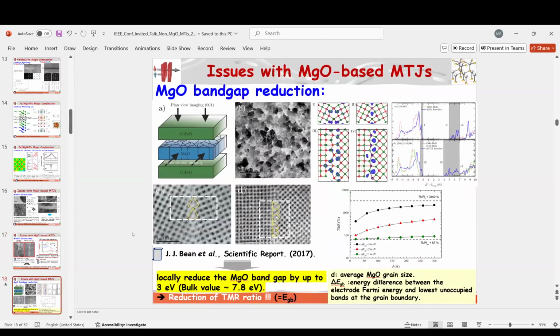I like this paper. It was published by York University and Tohoku University as a collaboration, Scientific Reports 2017. So they gathered the information from TEM, top view, cross view, they included DFT, and they tried to approach the experimental TMR ratios obtained experimentally. And they discovered the shocking, maybe, result that actually the MgO should have a low band gap.